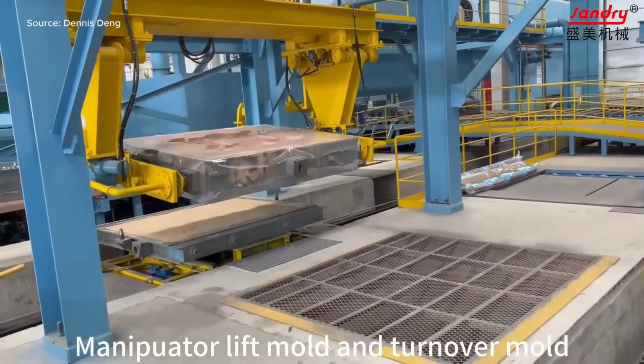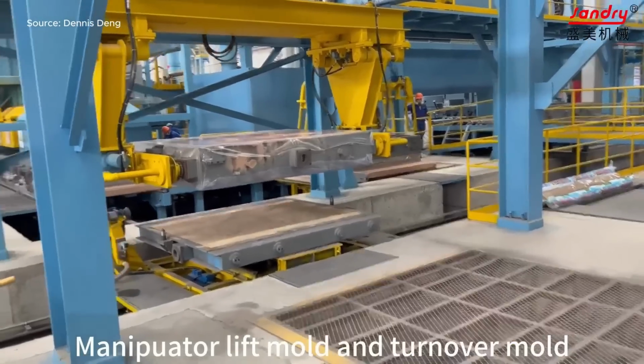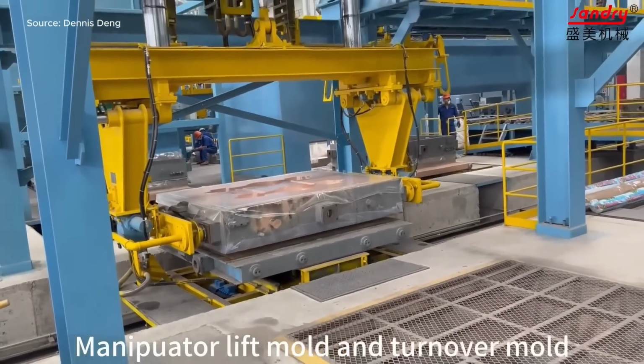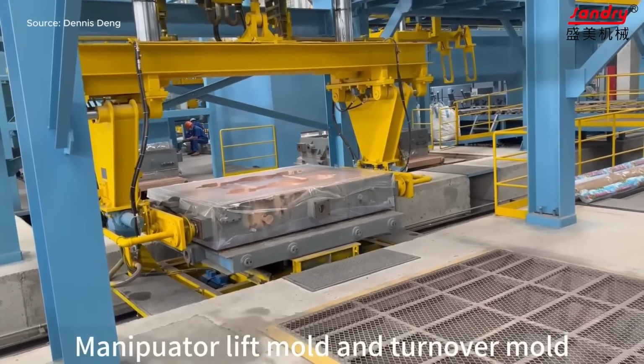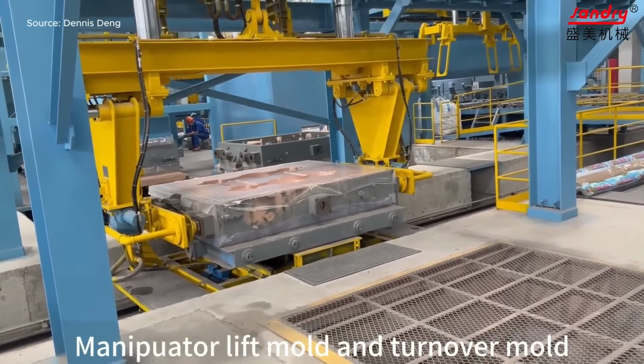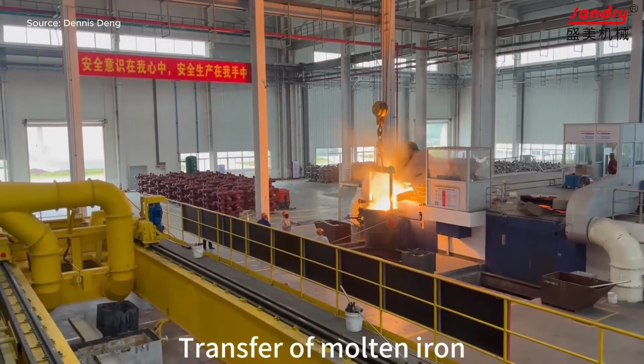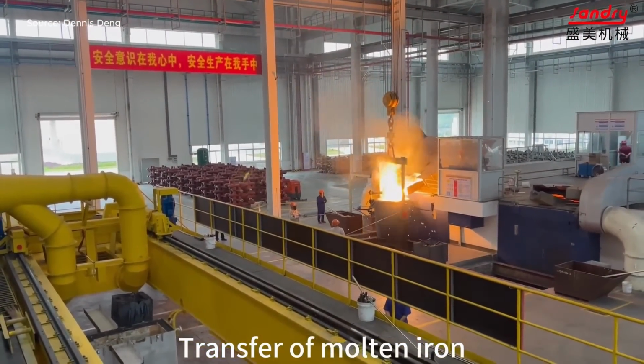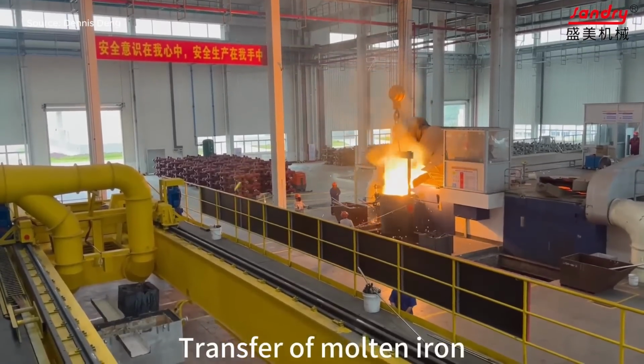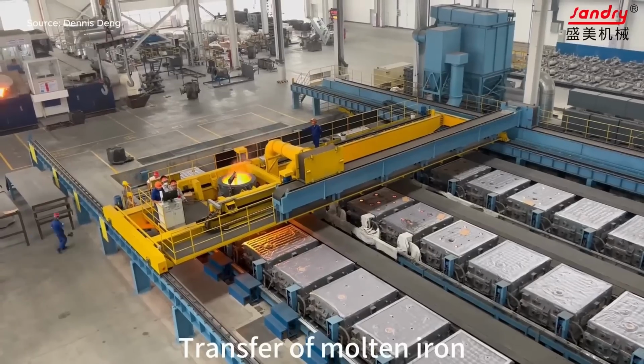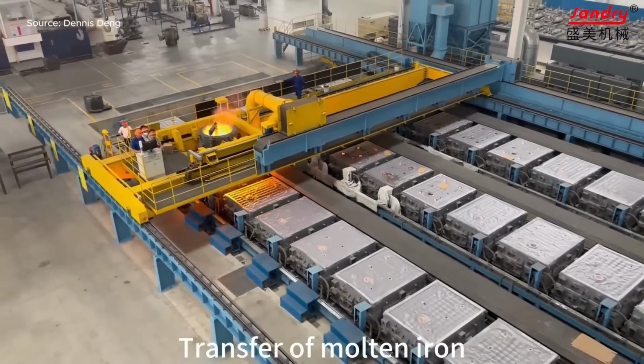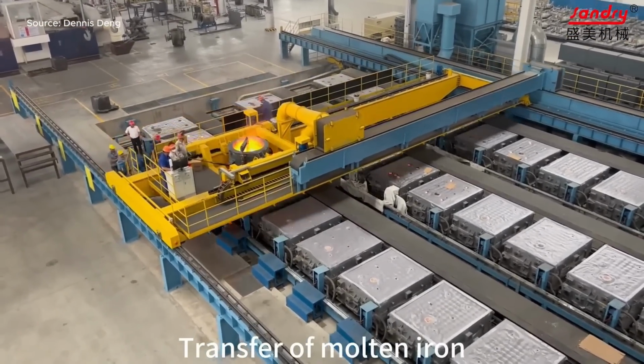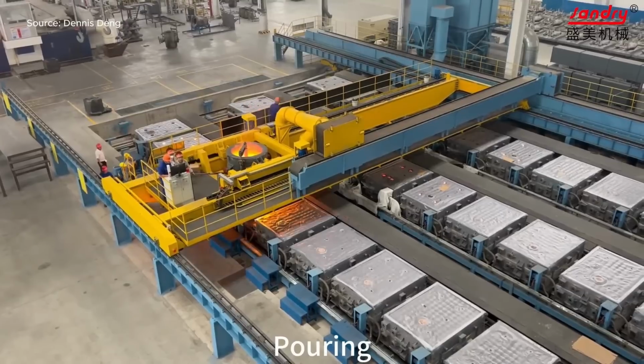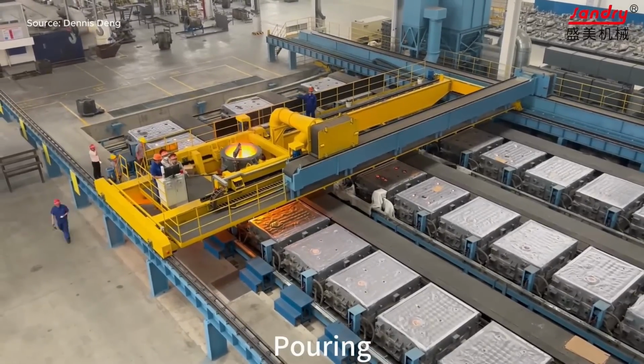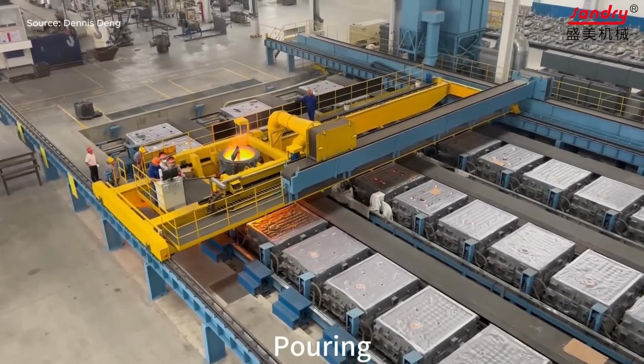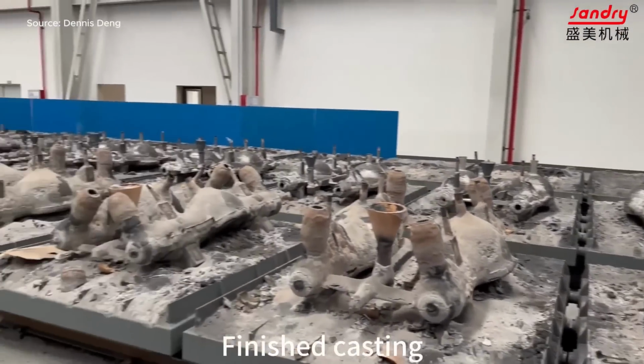The iron is poured smoothly into the cavity through the riser and cup system, ensuring even filling and minimal turbulence. After cooling and solidification, the vacuum is released, and the mold collapses easily, allowing the casting to be removed without damage. The V process offers high-dimensional accuracy, superior surface finish, and reduced post-processing. It also minimizes gas defects and allows for easy recovery and reuse of sand, making it both efficient and environmentally friendly, ideal for producing high-strength axle castings.